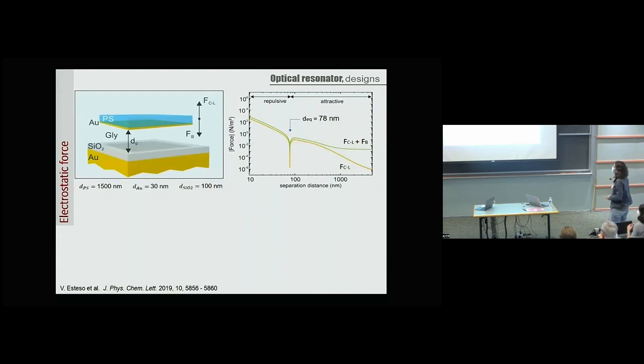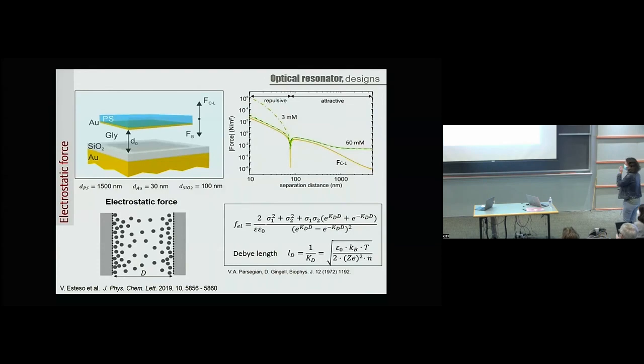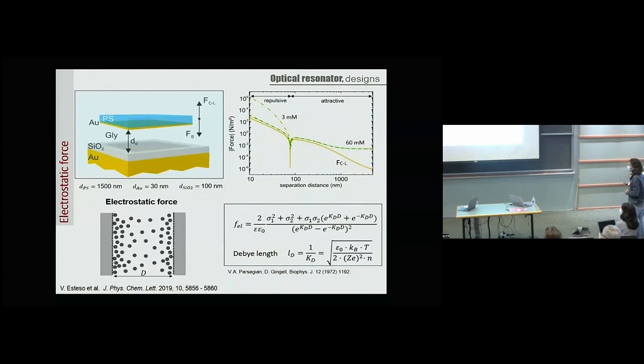And here I plot the total force acting on the system as a function of the separation distance. The yellow curve corresponds just to the Casimir force, and this also takes into account gravity and buoyancy. This is plotted in logarithmic scale because it is easier to identify this minimum here, which corresponds to the equilibrium distance at which this system will levitate. We have repulsive forces at short separation distances and attractive ones at long ones. We also analyzed the effect of electrostatic forces by employing the Poisson-Boltzmann methodology. We found that for monovalent salt at this large concentration, the equilibrium position was not modified at all. And even with low salt concentration, the equilibrium distance was hardly modified, although it also enhanced the repulsiveness of the system.